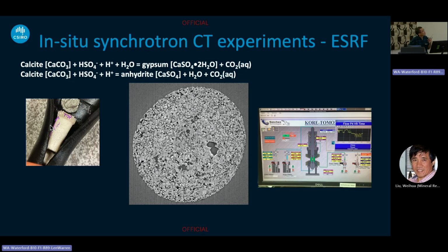This example is the one that we did at the European Synchrotron. Let's look at the replacement of calcite by sulfate-rich water to form gypsum, and also see how the porosity, for example, evolves in this flow-through system. You can see that this is the result from the synchrotron, where the minerals are being dissolved and forming these larger fluid pathways.